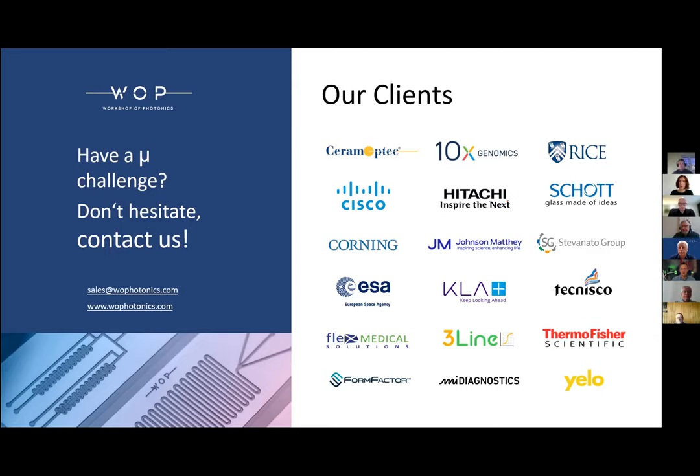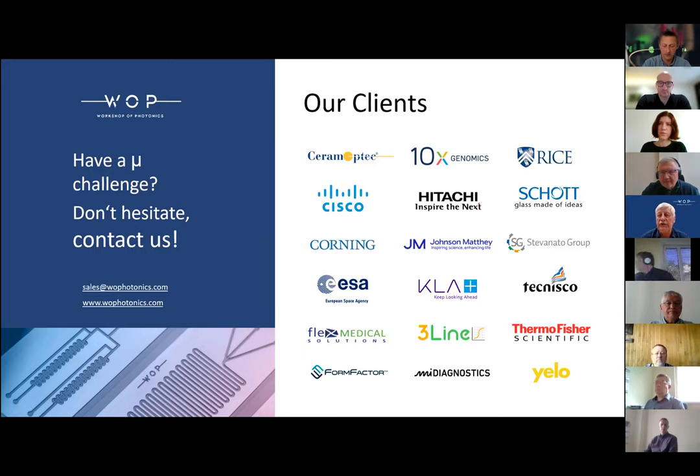Do we have any more questions from the audience? Yes, we have. Naren is asking, how do you produce multicolor laser patterns inside the glass, Antanas? It is quite a tricky process. We modify the refractive index along with producing some kind of periodic nanostructures we also use for manufacturing special optics. It is a separate field, needs quite good theory. Actually we inscribe birefringent structures, which are a couple of microns wide, and we organize them appropriately to get this colored scattering.